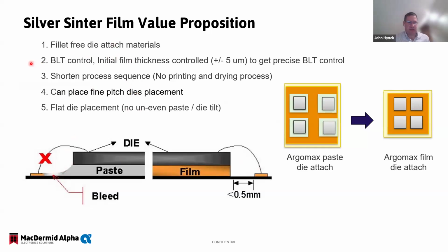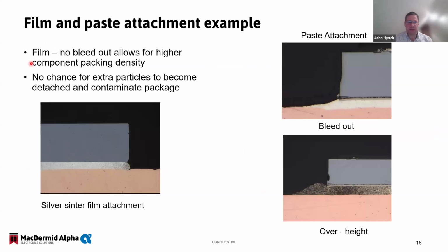Another big advantage, I mentioned this earlier, is bond line control. The initial film thickness is controlled to plus or minus 5 microns. That gives you precise bond line control. Typically with the typical film that we offer, the bond line is about 20 microns. The shortened process and the placement can be much better with film versus paste. I wanted to show you some cross sections that we've done that really show better than explaining what's going on.